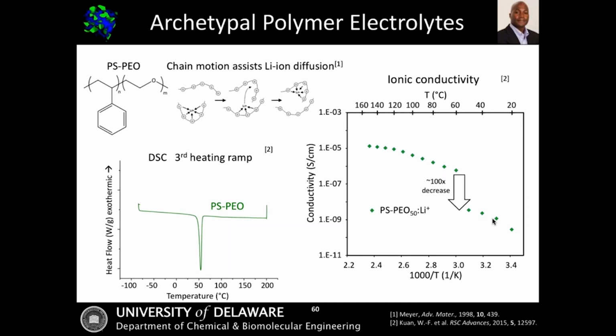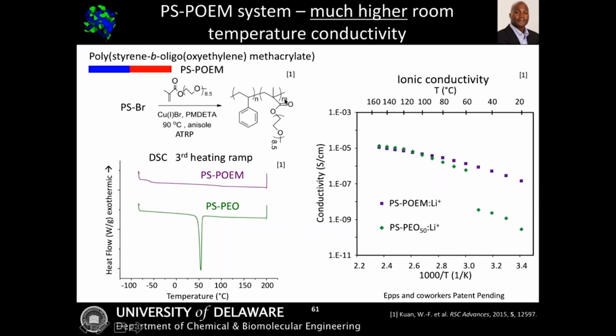So one of the things people have looked at is how I can get rid of that crystallization. One example is, instead of polyethylene oxide, to use a methacrylate-based material, very similar to some of the materials that Joe talked about with the ionic liquids. In this case, I've taken those ethylene oxide repeat units and moved them from the main chain to the side chain. By doing that, if we look at the DSC calorimetry data, I've eliminated that melting and recrystallization behavior. Given that, when I look at the conductivity data, when we go to lower temperatures I no longer have that discontinuity, and so I now have materials that are potentially useful for more room temperature applications.